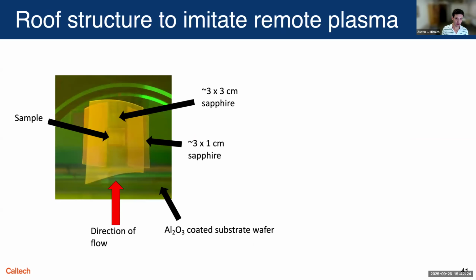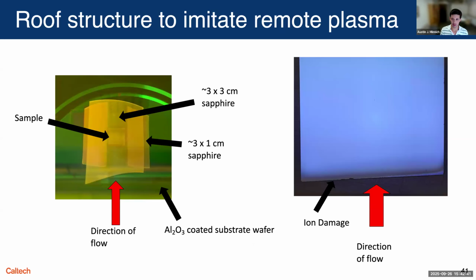So we had to get a little bit clever. We needed to use this tool for the moment, but we also needed to shield it from ions. So you can make a little roof structure where sapphire protects the sample, and you can still get these radicals in. And that worked pretty well. You can see the ion damage, which is the black region in the right image. It's kind of confined to the edge of the chip, but the rest of it looks pretty clean.